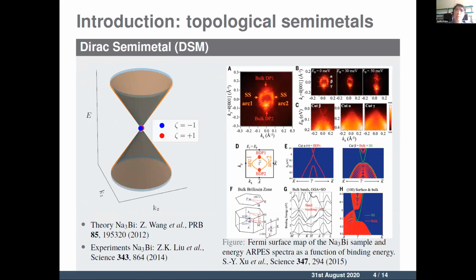A simple Hamiltonian like the former one can be used to build topological Dirac semi-metals. In fact, each Dirac point can be constructed by imposing two Weyl nodes with opposite chirality, leading to a net chirality equal to 0. In this scenario, the Fermi arcs come in pairs and connect the Dirac points, precisely as two copies of Weyl semi-metals. Compounds such as sodium bismuthide and cadmium arsenide show this pair of Fermi arcs, and the manufacturing of high-quality thin films and ultra-thin films of sodium bismuthide has made the material one of the most promising candidates for technological applications.